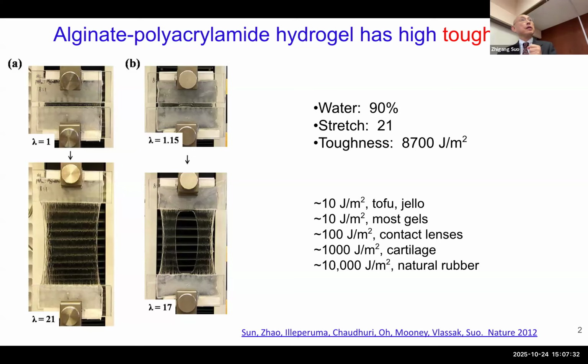enormous toughness. Now in mechanical engineering, everybody is a mechanical engineer. We know what toughness is. Toughness is a resistance to crack growth. So in particular, this material is transparent, so you see the black background. This material can be stretched 21 times. It's a very stretchable material, more stretchable than rubber.